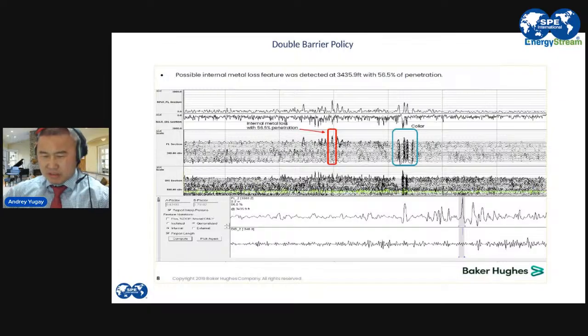So same MVRT log, what we can see on the flux log, we can see on the sensor, we can see corrosion. However, internally, the discriminator shows that internally the casing is fully corroded all the way from top to bottom. Okay, so what is the message from this slide is that if we ignore subwells, if we ignore exposure of the secondary barrier to the well media, and sometimes it is not really designed for the long-term exposure, then we can lose the well completely.